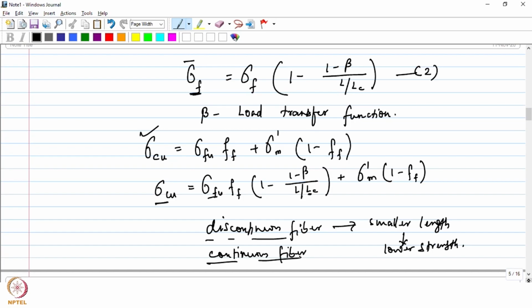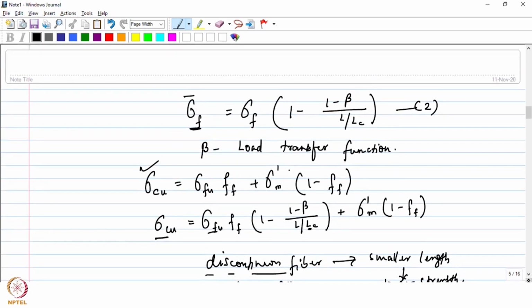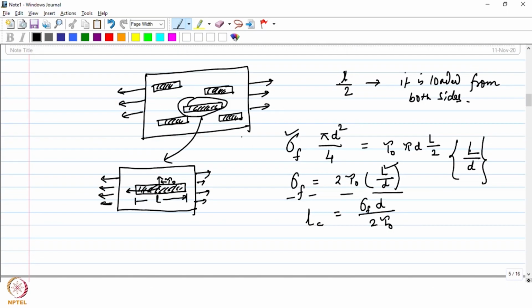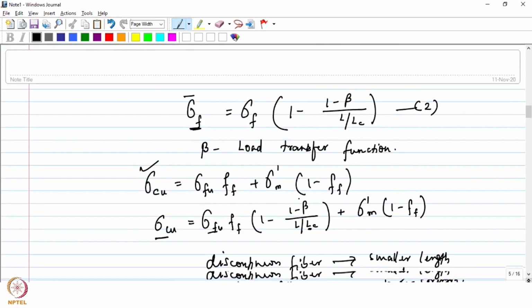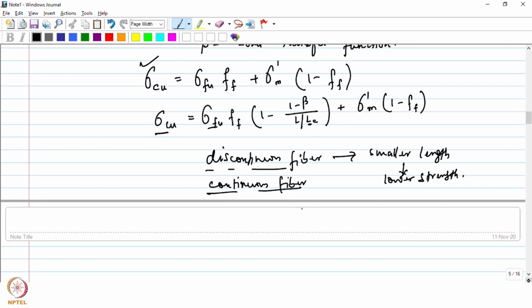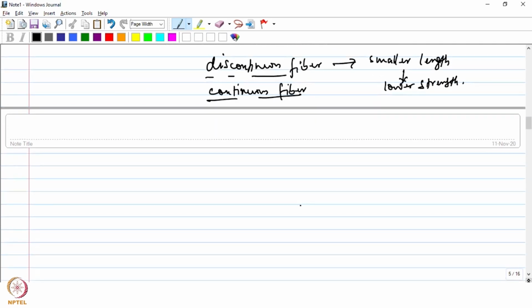So now it can explain the actual observations, what you practically see, which was not possible to explain by the rule of mixture model, right? So practically you would see if you vary the fiber geometry, the strength will also vary, right? And that is how this shear lag model takes into account the geometry or the dimensions of the reinforcement, okay? So it tells you that as you change the dimensions, the strength will also differ, okay? And that is what we practically see. So this model is able to explain the actual observations that we see in reality.